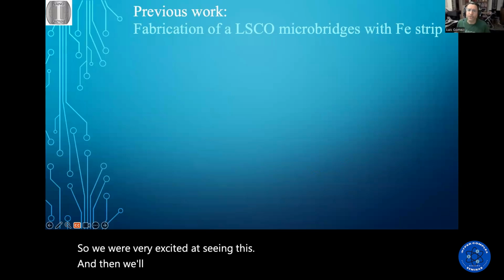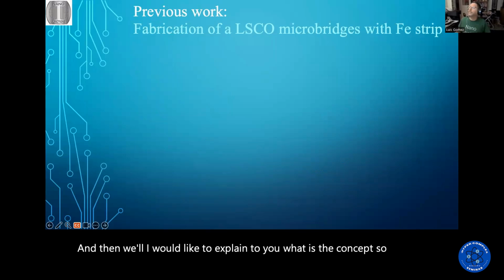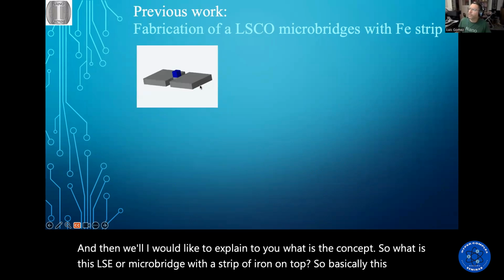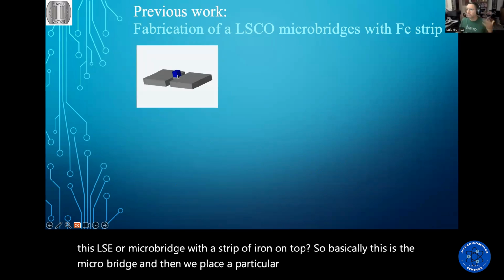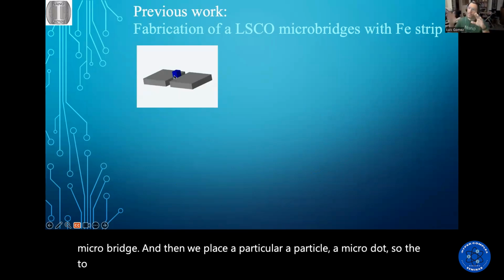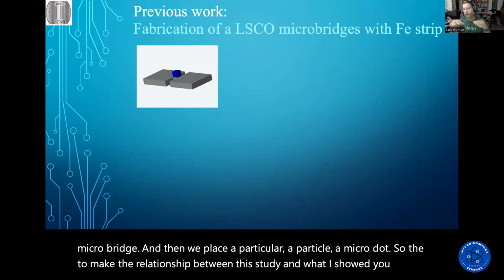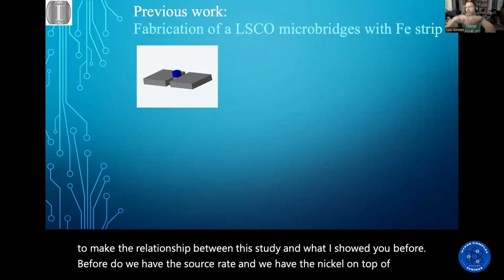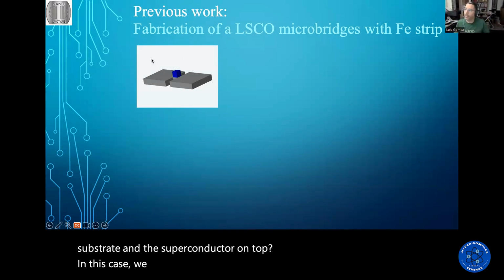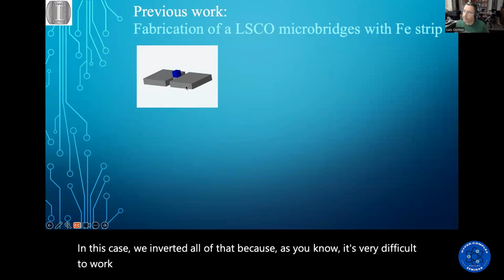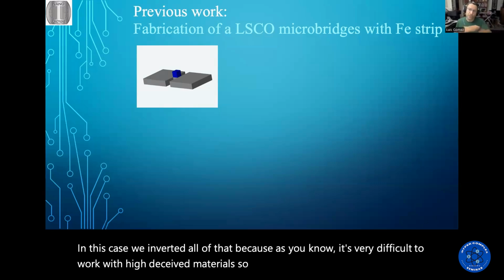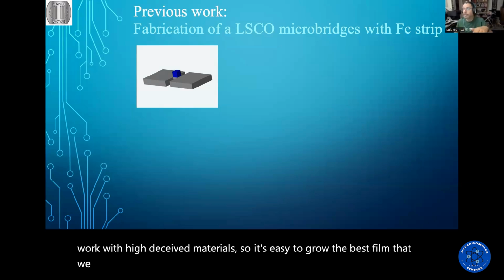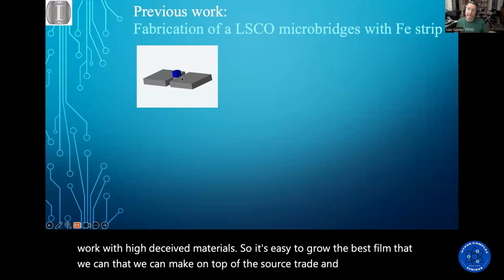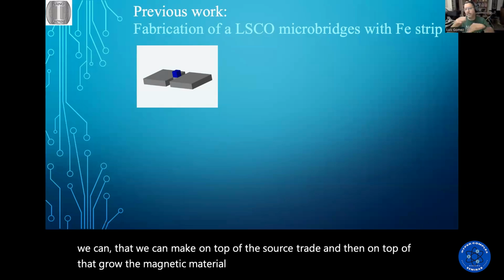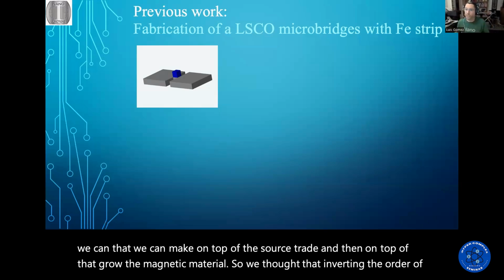Then I would like to explain to you what the concept is. So what is this LSCO microbridge with a strip of iron on top? Basically, this is the microbridge, and then we place a particle, a microdot. To make the relationship between this study and what I showed you before: we have the substrate, the nickel on top of the substrate, and the superconductor on top. In this case, we inverted all of that because, as you know, it's very difficult to work with high TC materials. So it's easier to grow the best film that we can make on top of the substrate, and then on top of that grow the magnetic material. So we thought that inverting the order of the process wouldn't change things.